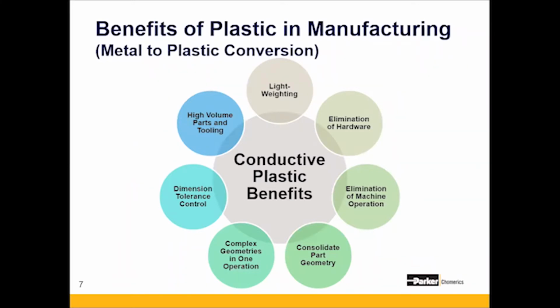And you can also mold with no machining for really high tolerance fits when it comes to under an inch diameter type designs. So building off of that a little bit, instead of machining several parts, the nice thing about plastics is that you can mold a single complex geometry in a single go. So what that means is that the tools can include very thin walls that would typically require hours of machining or several sheet metal parts.